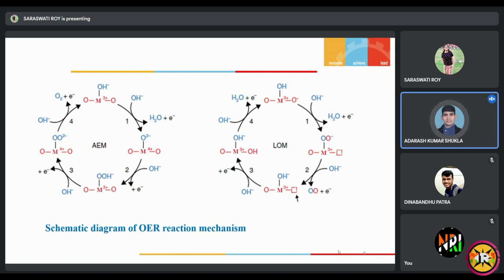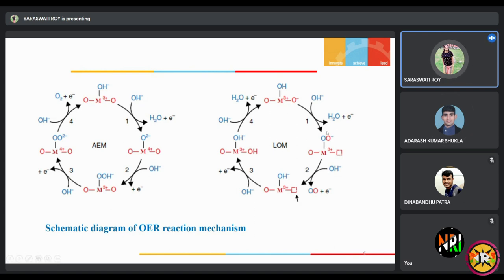Actually, the mechanism you have shown, how could we say that this is the pathway of the OER reaction mechanism which your catalyst is following? Actually, for my catalyst, two things are happening. As you can see here, for LOM, lattice oxygen mediated, there will be the formation of oxygen vacancy, and for AEM there will be a change of the metal oxidation state. As you can see, from step 1 to step 2, it is the conversion of 3 plus to 4 plus.